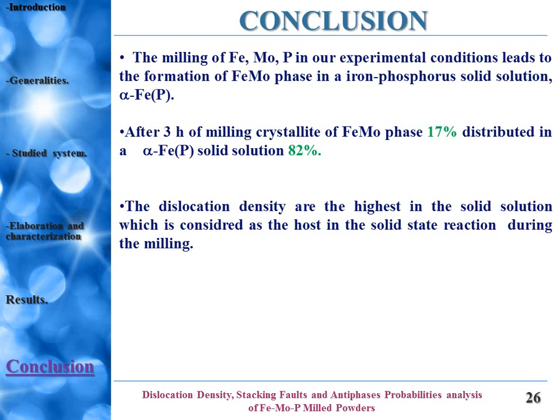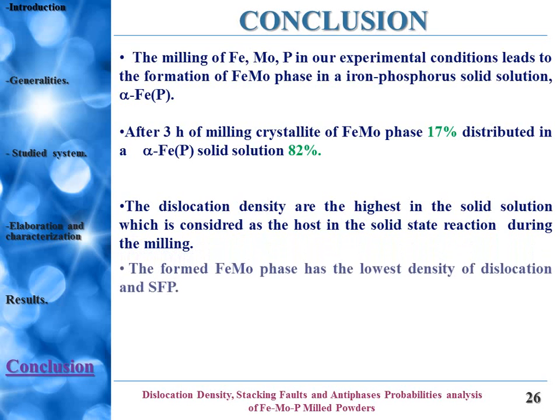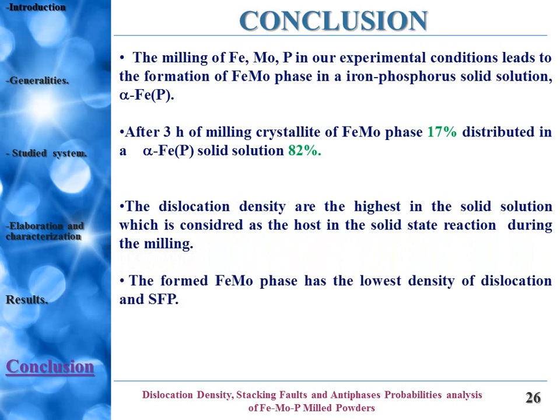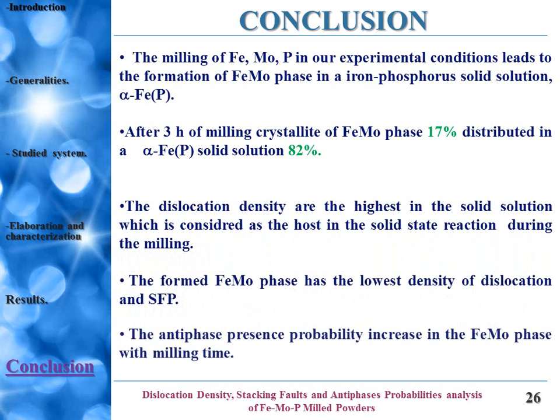The dislocation density is the highest in the solid solution, which is considered as the host in the solid state reaction during the milling. The formed iron molybdenum phase has the lowest density of dislocation and SFP. The antiphase presence probability increases in the iron molybdenum phase with milling time.